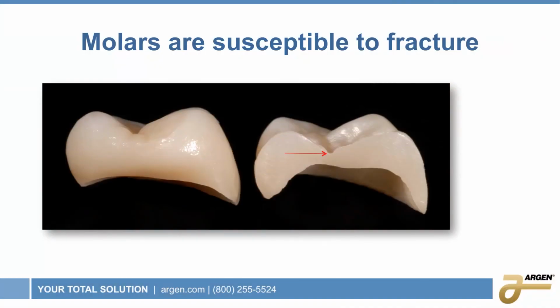And that's one of the things that Dr. Christensen actually addressed. So molars are particularly susceptible to fracture, number one, because that's the highest stress area. And number two, we have a built-in crack starter in the occlusal fossa. Don't try and keep that sharp. Let that round out during the sintering operation, because that will actually stop the crack from happening.